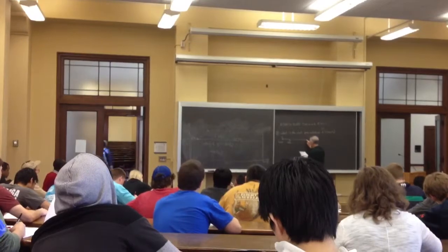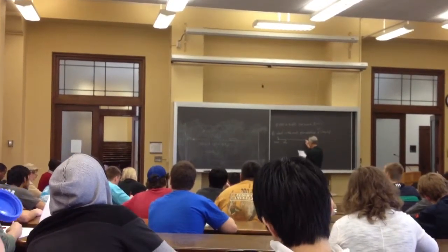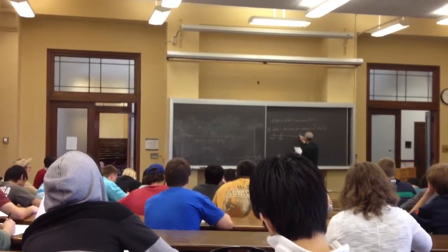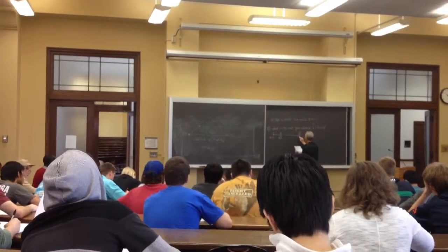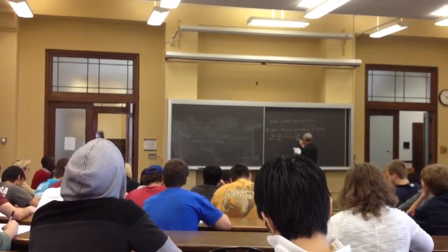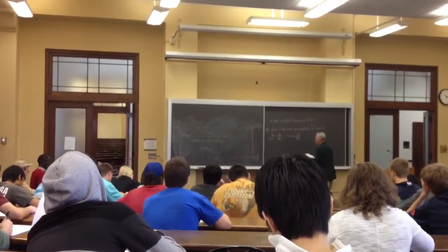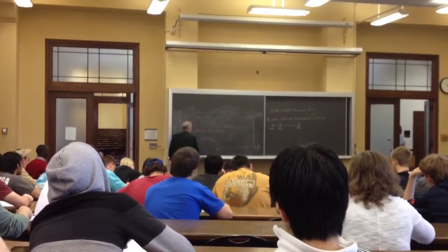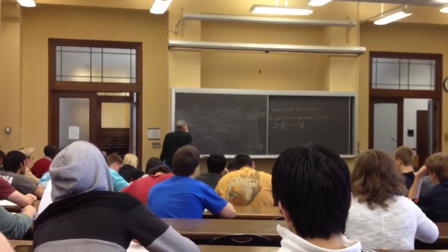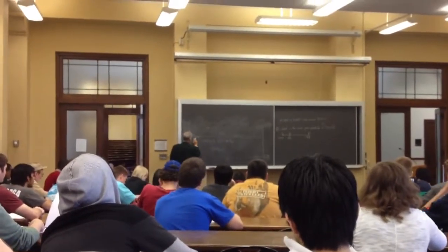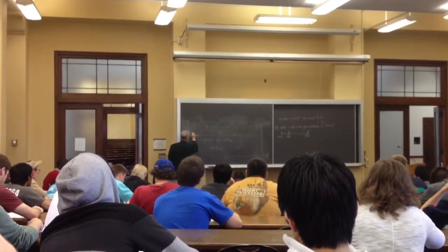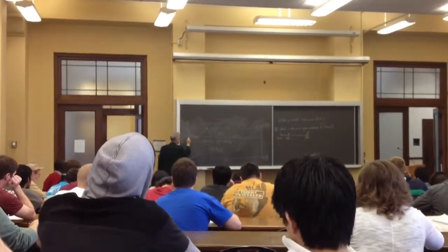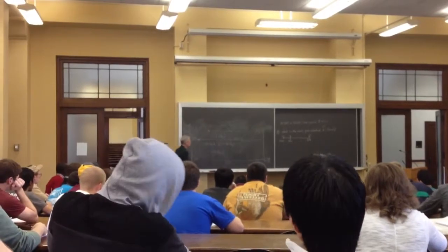And out to here, we're going to call this AB, B prime is at 0.8. Okay. So the amount of pro-eutectoid ferrite that's coming out is going to come out as we cool down through here because it becomes more and more alpha. The alpha is lean in carbon, and so the gamma becomes rich in carbon.